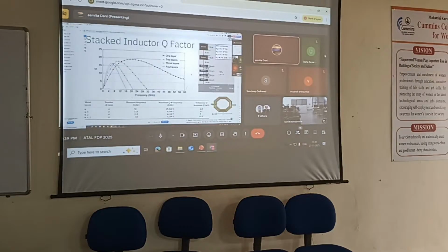So this is an example in which they have a CMOS process where they have a substrate and then 6 metal layers on top. Okay, so they have designed this spiral using different metal layers. If we look at the inductor that is designed only on a single layer, it has 4 turns. Number of turns is 4 on the spiral. We see that the self-resonant frequency is 50 gigahertz, and the maximum Q it has achieved is 15.2. Okay, but the inductance value is 1 nanohenry. Then they use layers 6 and 5.